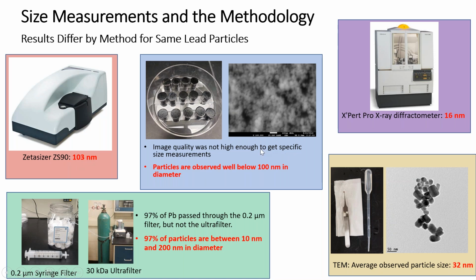If I look at the scanning electron microscope, we can't quite make out the particles. It's difficult to see. There's a lot of them on the filter. But if you look close enough, and the measurement bar is here, trust me when I tell you that most of those particles are less than 100 nanometers, but that's about as good as you can get because you can't really see them very well.